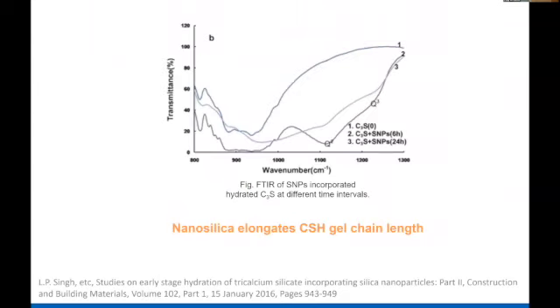Another one, we found out that the calcium silicate hydrate that is produced after the reaction has a higher chain length than microsilica or normal CSH. And this is shown here from FTIR results, and there are Q3 when you have nanosilica. And I know that Professor Shi has done similar work with GO, using NMR, showing that the nature of CSH and calcium hydroxide crystal is different when you have this graphene-based material. So this is very different than a conventional